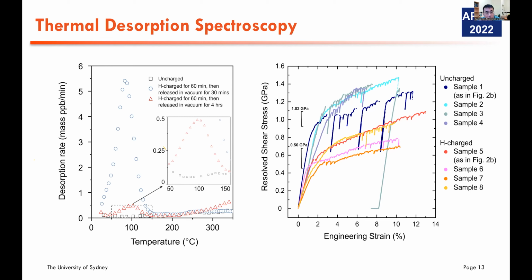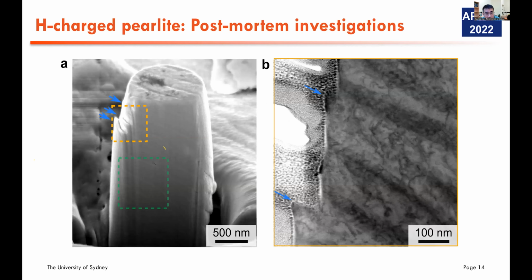And we cut the cross-section of the hydrogen-charged, compressed pillar, and when we check the interface, surprisingly, we see that the slip is no longer exactly at the interface. And why is that? So we try to see where hydrogen is in the charged pearlite sample.